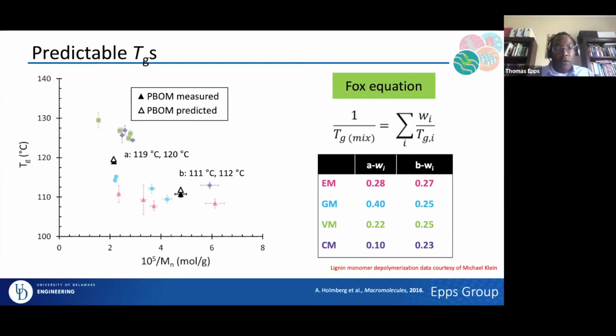And so here's just one example of how we were able to do that. And I'm going to spend just a minute on this slide kind of walking you through a little bit about what happened here. So one of the first things is that we were able to get this depolymerization data courtesy of Mike Klein, who basically did a computational analysis of Kraft pine lignin depolymerization, in this case through pyrolysis. This is the only slide where I'll mention pyrolysis in terms of what we were doing. Anyhow, what he was able to do is actually through his computational modeling of the kinetics actually predict what would happen in terms of distributions of monomers in column A versus B, where the only thing that's different is the pyrolysis temperature of 550 degrees versus 600 degrees.